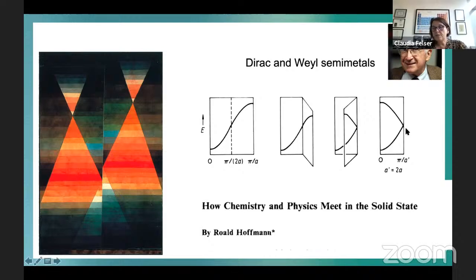And this is also why this is not very uncommon. Crossing points, which show this linear dispersion in the band structure like in graphene, and you've heard a lot about graphene, are also quite common because it's a simple feature of band structure. The question is whether the Fermi energy is exactly here to see the nice properties in transport, and this is very nicely seen in a simple band structure, really exactly in graphene.